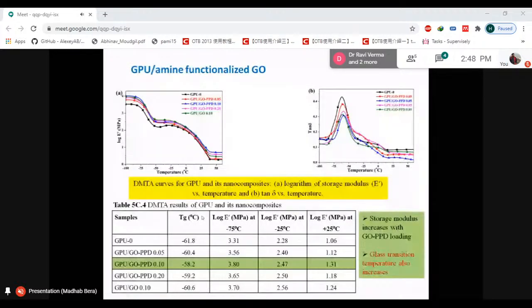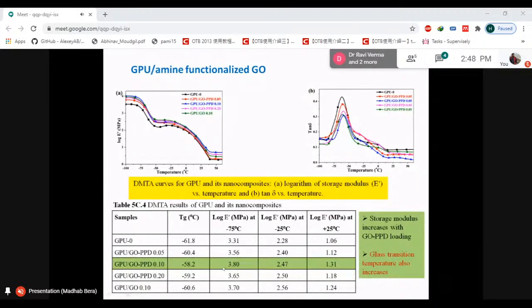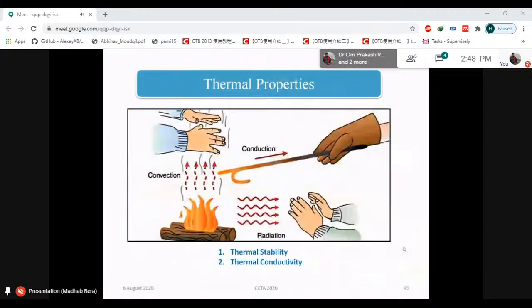Now, a similar phenomenon is observed for glycidyl terminated polyurethane, that is epoxy modified, and the amine functionalized graphene oxide. The storage modulus increases with increasing GO-PPD loading, and the glass transition temperature also increases, but it is very small. So we can neglect this improvement because it is only 1 or 2 degrees. So this is good for low temperature application of this material.